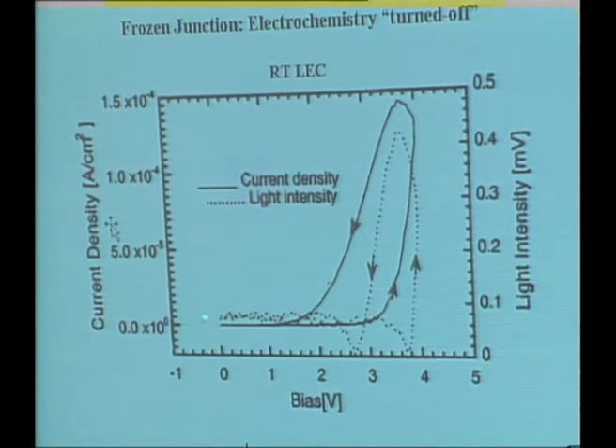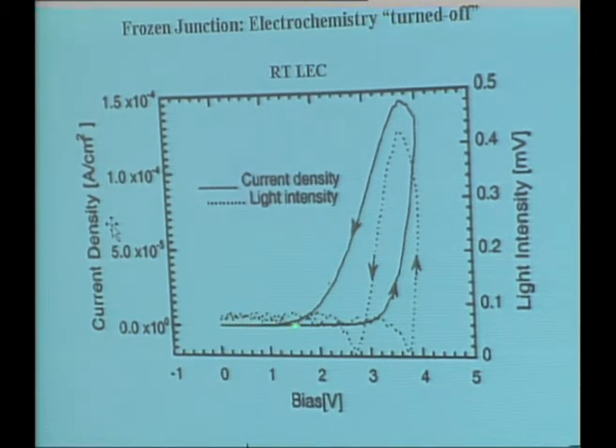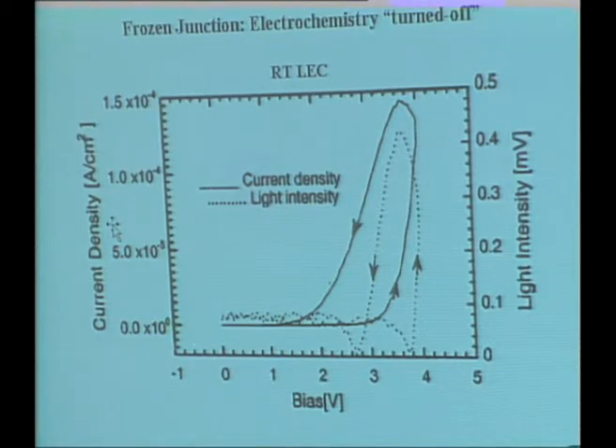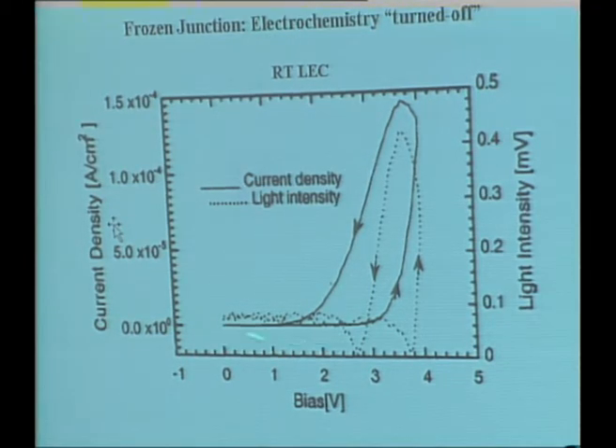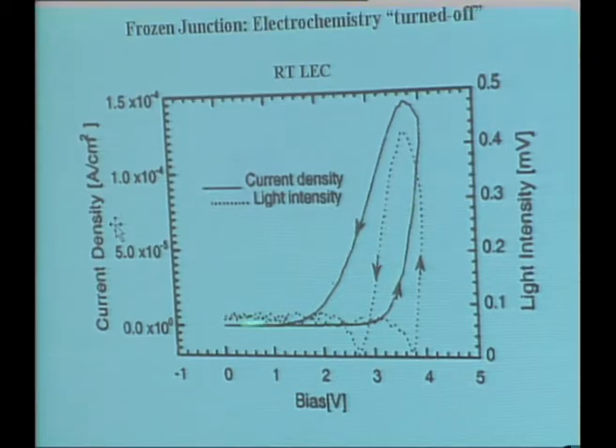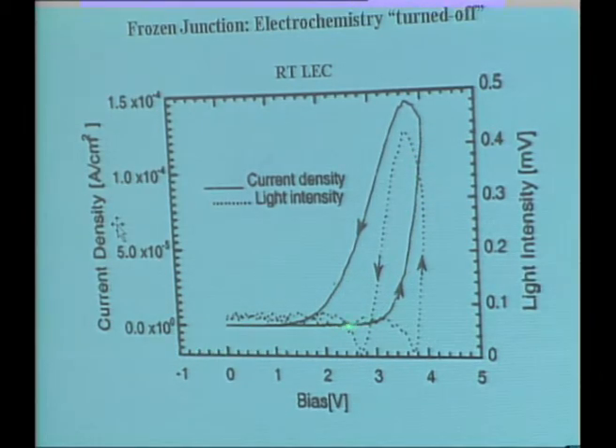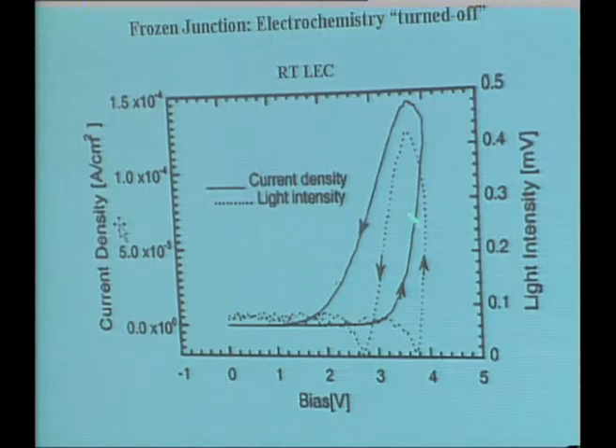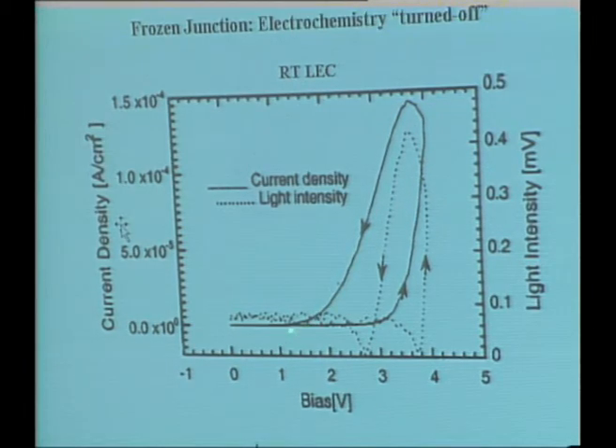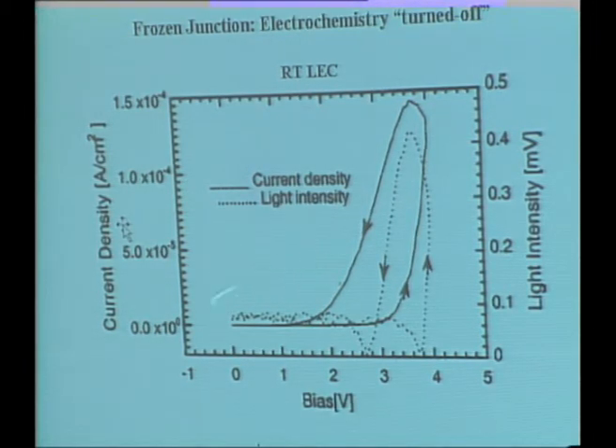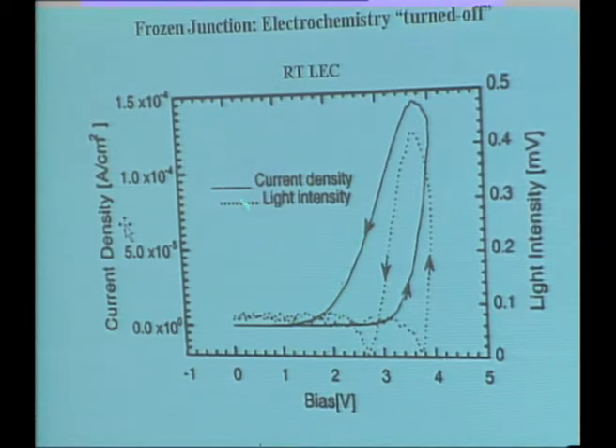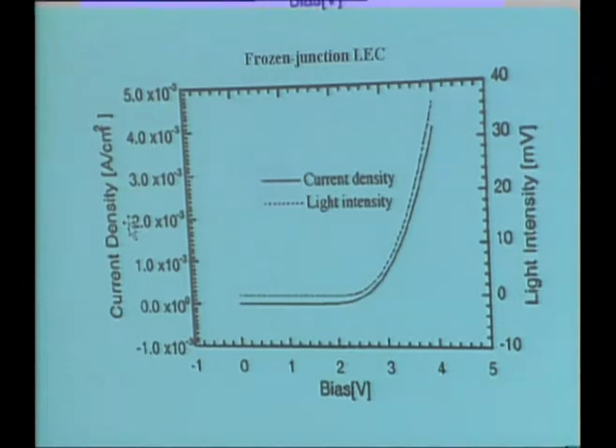If you look at the current versus bias at room temperature, where the junction is forming and reforming, the ions have to move, and so you tend to get hysteretic effects of this kind, okay? Because you're building up the ionic doping here. You're creating the doped regions here. You're undoping over here, and there's a natural hysteresis both in the current density and in the light intensity. But if you freeze the junction and go down to low temperatures, then it's just a PIN junction like you would find in an inorganic semiconductor.